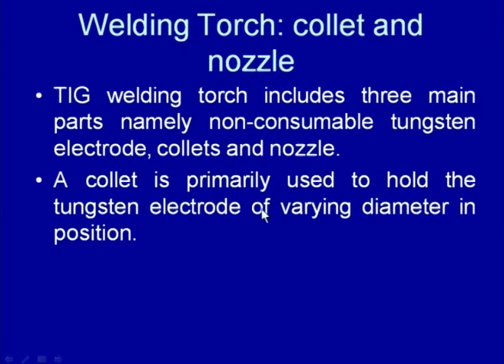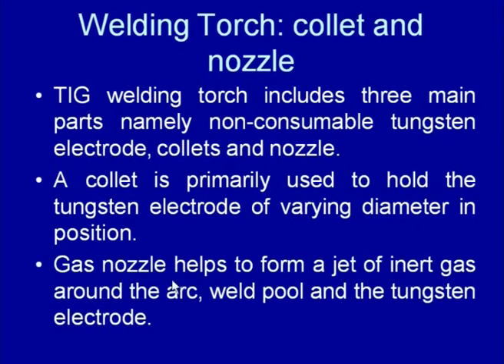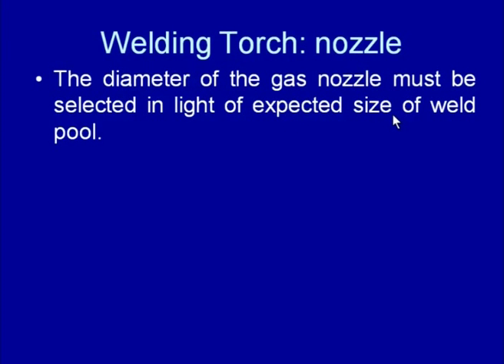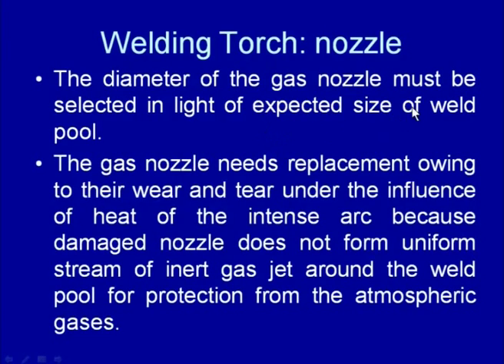Collets are designed to accommodate electrodes of varying diameters, and when the electrode is placed in position and the arc is struck, the flow of gas around the arc is started. The gas nozzle helps to form a jet of inert gases around the arc, so that the weld pool and the tungsten electrode can be protected from atmospheric contamination. Further, the diameter of the gas nozzle must be selected in such a way that a very effective and sound jet around the arc is developed, so that the weld pool can be protected from atmospheric contamination.